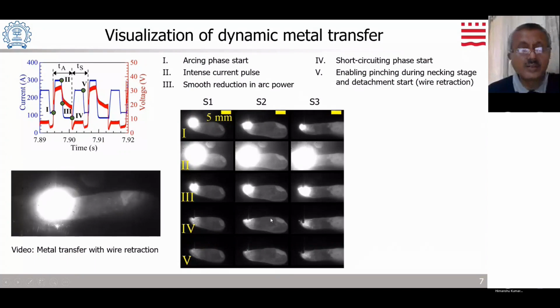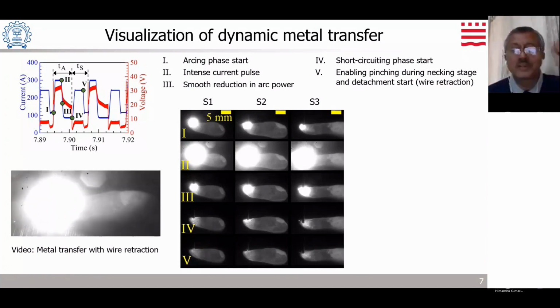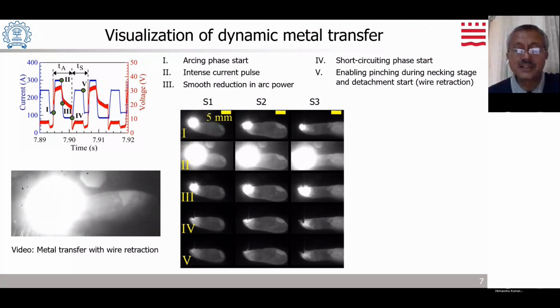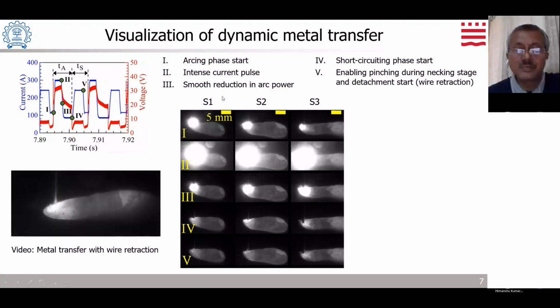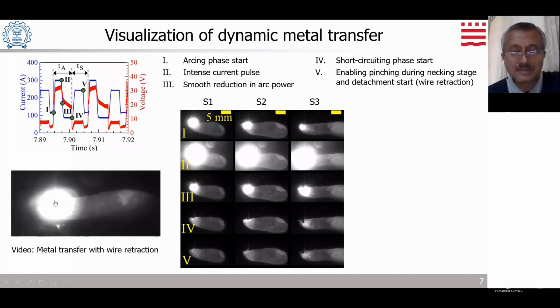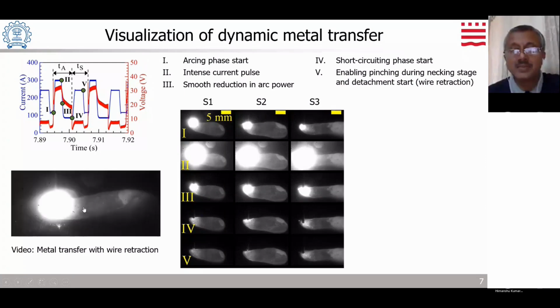These are all three regular processes. At this very moment, I don't have a situation where there is a lot of disruption, but you can see in a case where these parameters or process conditions are not set properly, there will be a lot of spatter, which will of course increase the process instability and also dimensional inconsistency of the final bead. So this is the contribution of the video camera over the real-time monitoring.